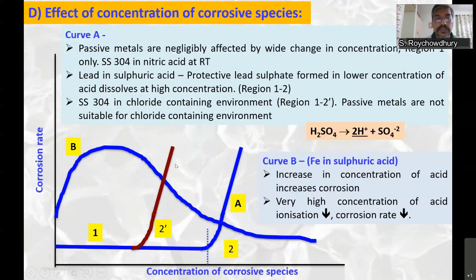This increase in corrosion rate can also occur at very low concentration. This is mainly pertaining to the presence of chlorides. If chlorides are present, then the corrosion rate increases rapidly at very low concentrations of chlorides. This is mainly due to pitting corrosion in alloys which rely on passivity for corrosion protection. Another possible behavior is this curve B, for example, like iron in sulfuric acid.